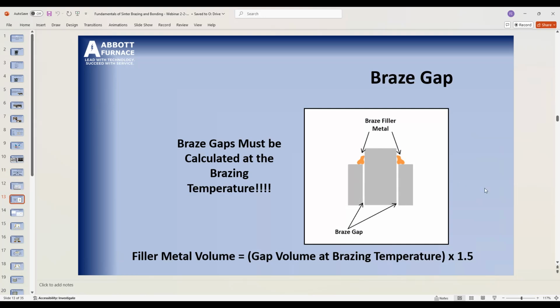The reason we want extra is, when you look at a really good braze joint, you see these fillets on the ends of the braze joints. You want to see nice fillets. They're not what gives you strength, but they tell you that it pulled through and gave you a good bond inside. The other thing is, do not put filler metal on both sides of a gap, because then you don't know if it pulled through.